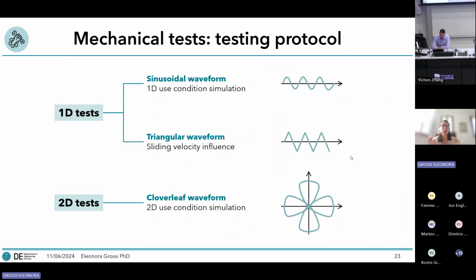The testing protocol consisted of monodirectional test and bidirectional test. For the monodirectional test, I applied a sinusoidal waveform to assess the monodirectional real use condition for the device, a triangular waveform to identify any influence of the sliding velocity on the performance of the device. And finally, I performed a bidirectional test using a cloverleaf waveform to assess the bidirectional behavior of the device in a real use condition.